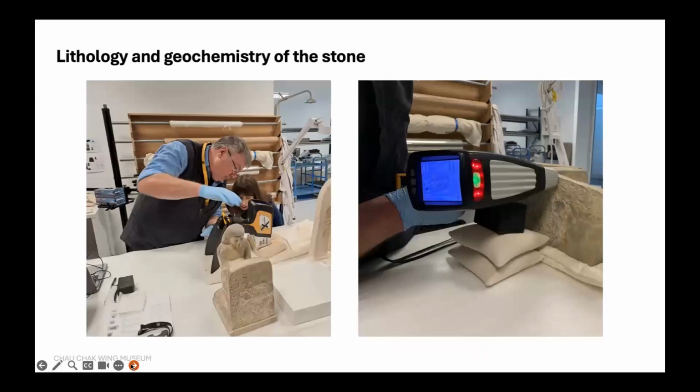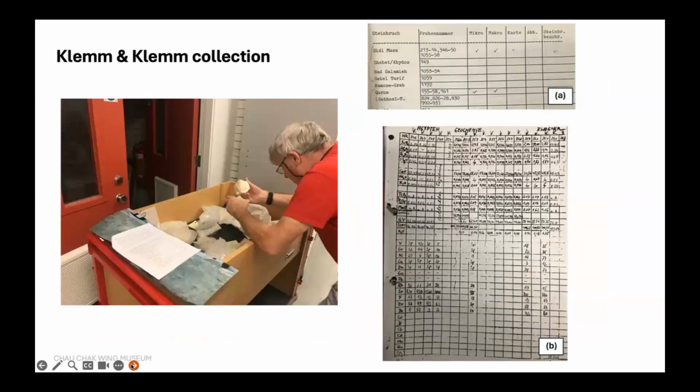Now, as with the Hemi-Ra project, we have examined the lithology and geochemistry of the stone and undertaken XRF and reflective qualitative color analysis of the stelae. This work was undertaken by Professor Damien Gore, pictured here, of Macquarie University in Sydney, and then compared to measurements made on selected samples of limestones of known provenance, so 44 samples from 9 known locations with supporting XRF analyses by Trevor Emmett, who also worked with us on the Hemi-Ra door.